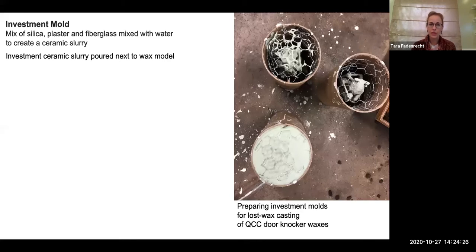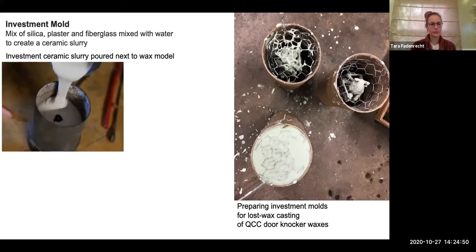So we like to put a thin coat, a skim coat of this over the surface to really make sure we get into all those cavities that have been carved, and also to prevent any sort of air bubbles along the surface of the wax. Anything that is a positive within the mold or is a negative within the mold, so an air bubble will end up being a positive on the other side in the metal.